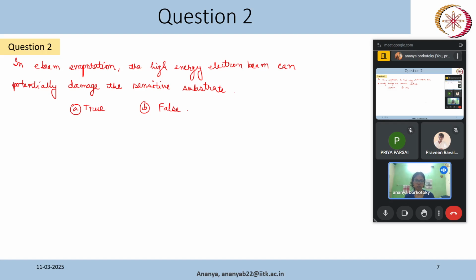So you cannot use it. It can create some stress, some deformation if you are using some flexible substrate. And another thing is that, as I mentioned earlier, you have already some photoresist pattern on top of your substrate, and again, photoresists are polymers. And if you want to do deposition on top of it, and you will etch it later, or do a process called lift off later, then your photoresist property will change, because with that heat, some kind of chemical reaction will happen. You will not be able to remove your photoresist as easily as possible.